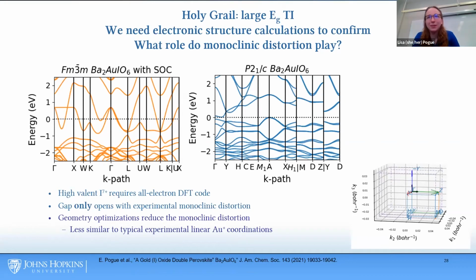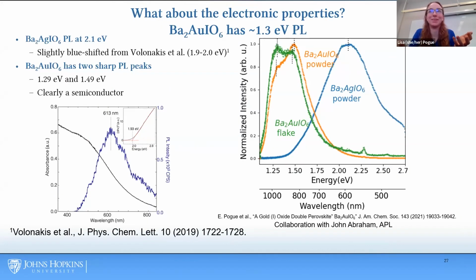The holy grail here would have been a large band gap topological insulator. And to determine this, I needed to do some calculations. This here shows that the monoclinic distortion we observed in experiment is actually critical to understanding electron transport in these materials. I was able to show that the monoclinic phase is necessary to actually get any gap. Otherwise, it tends to be a metal in calculations. And clearly, this is not a metal.